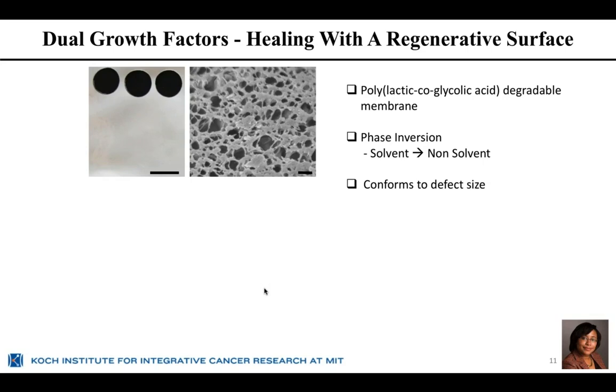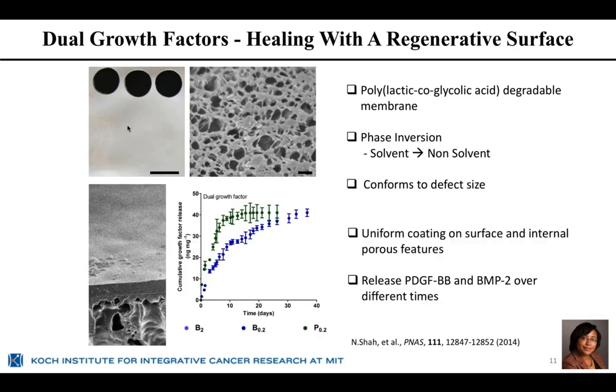a very standard phase inversion approach. It's porous and creates a surface on which we can then build our layer by layer film. The membrane then acts as a physical and mechanical support that degrades, and our layer by layer thin films coat that support, and without changing its mechanical properties, can release potent amounts of growth factor.